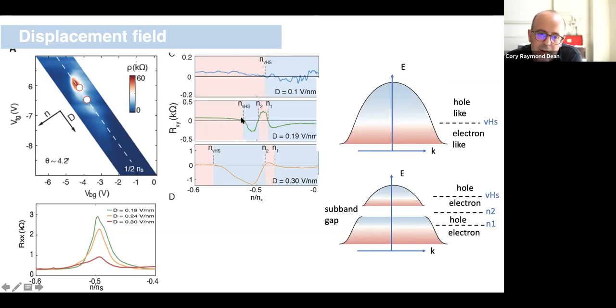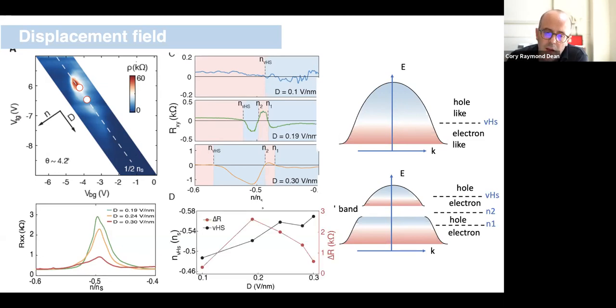So we're going to track this value, N Van Hove singularity, and assume that it basically tracks with how we might imagine the Van Hove position evolves as a function of applied displacement field in a single particle picture. That's our interpretation. Okay, so what do we see? What we see is that this quantity we call the Van Hove singularity, its position as a function of displacement field, begins slightly below half filling, and then as we increase the displacement field, it moves through half filling and then moves far away, to a much higher density.